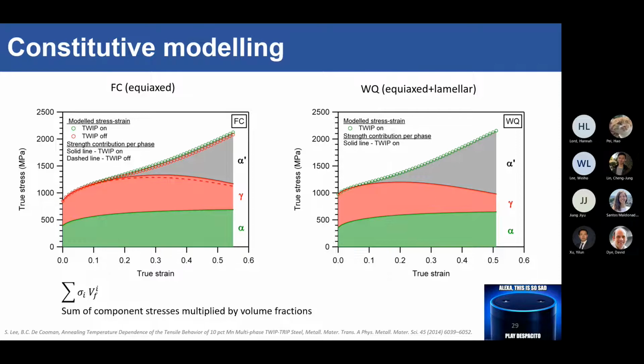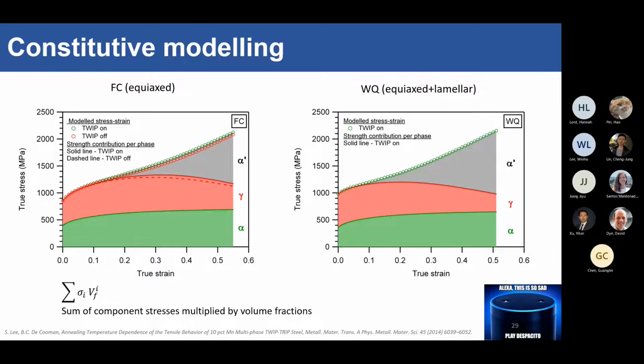And this is the dynamic Hall-Petch. And also, you are continuously losing austenite to martensite transformation. So the amount of austenite you have left to twin constantly decreases. And that's why the contribution from austenite actually goes down with strain. So what this again means for medium manganese steel is that we really need to reevaluate how we look at medium manganese steels as a manganese-lean TWIP steel. It's actually a manganese-rich TRIP steel, in fact, now.